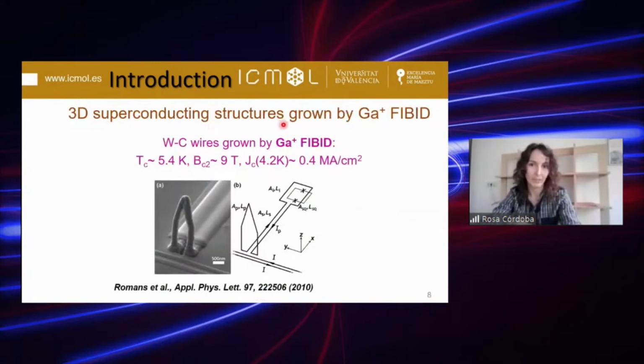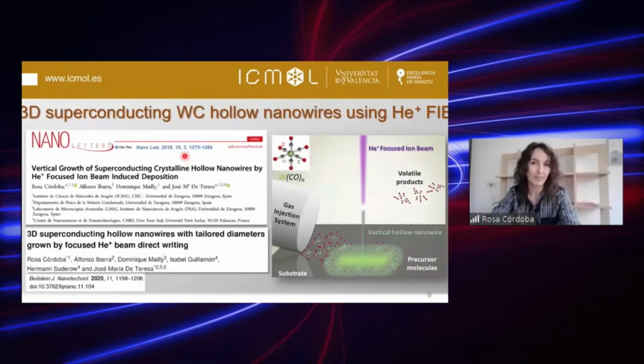So this is one example of 3D superconducting nanostructures made using a gallium focused beam, the same material that we were using for in-plane structures, tungsten carbon, and the superconducting properties, the critical temperature and the critical magnetic field, are very similar to those obtained in planar structures. But as you can see in this image, the resolution that we can get is very poor. The diameter of these wires is just 250 nanometers, and there is a huge proximity effect that prevents us from creating individual superconductors very close to each other without any kind of electrical connection. So today I'm going to present two examples of the fabrication and characterization of three-dimensional nanosuperconductors.